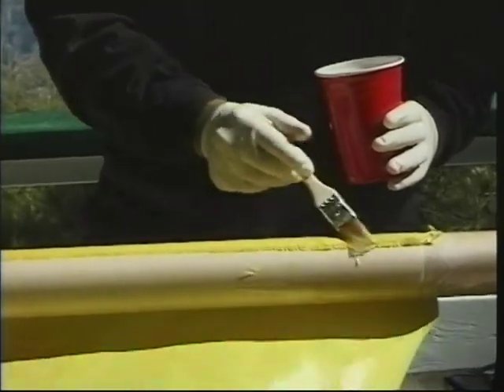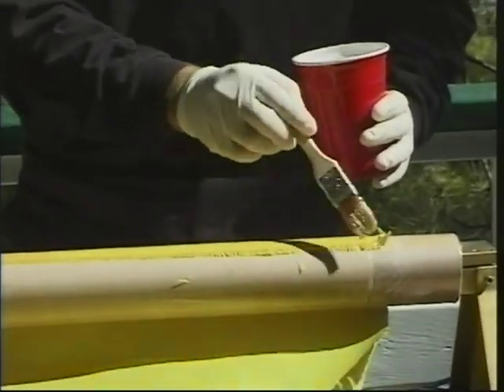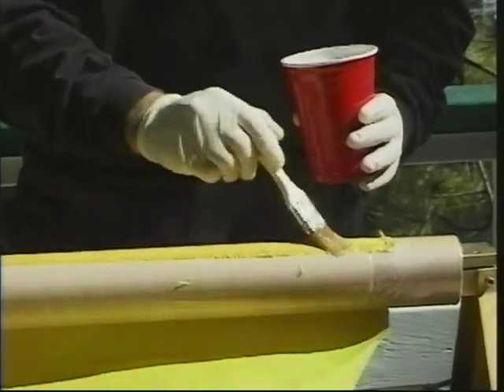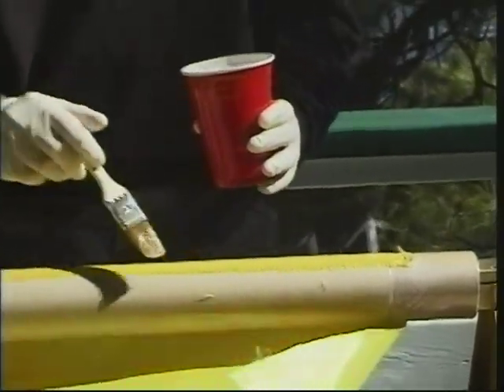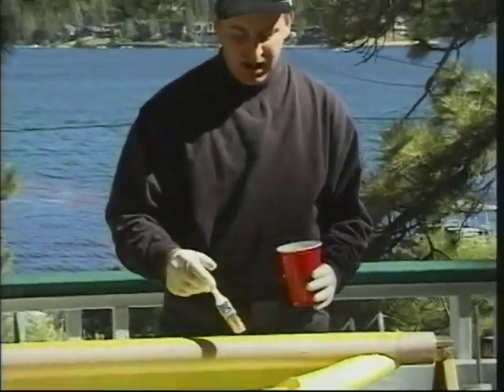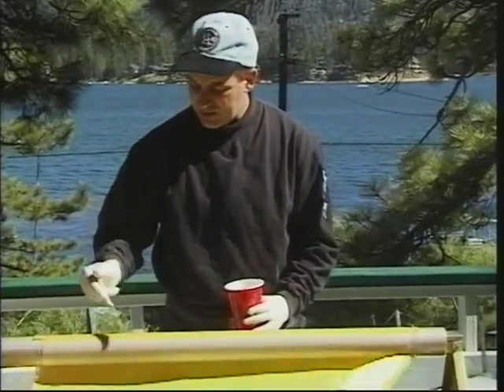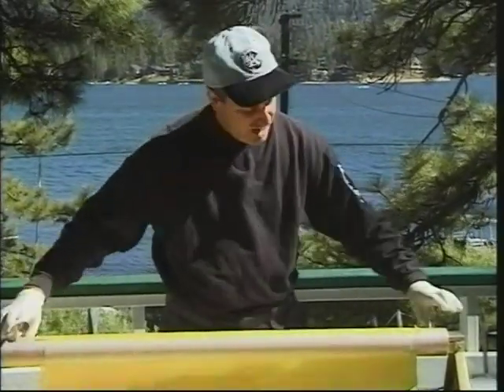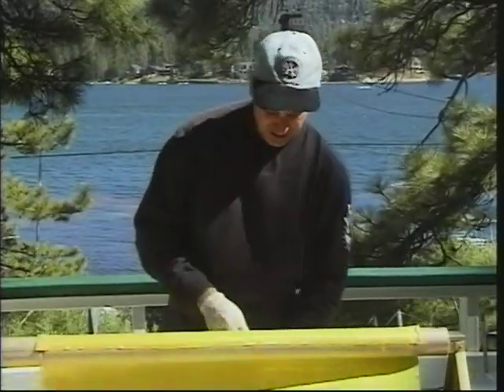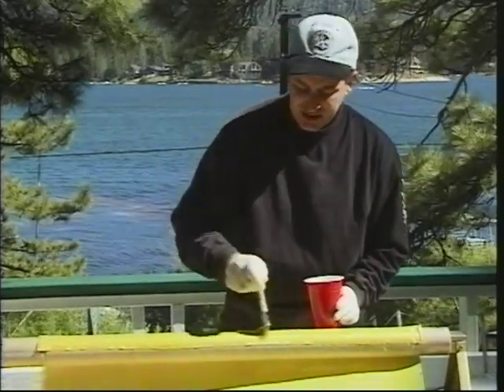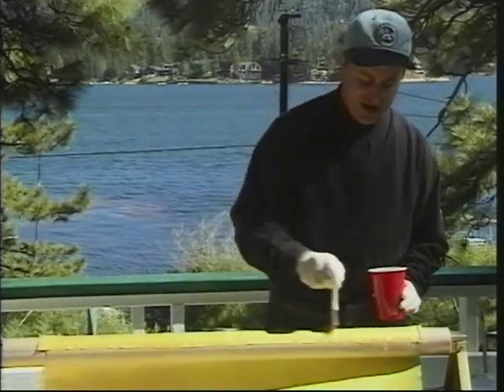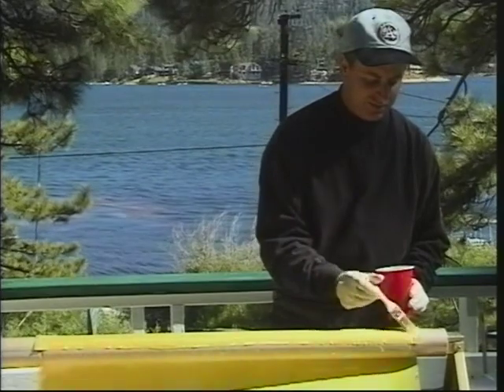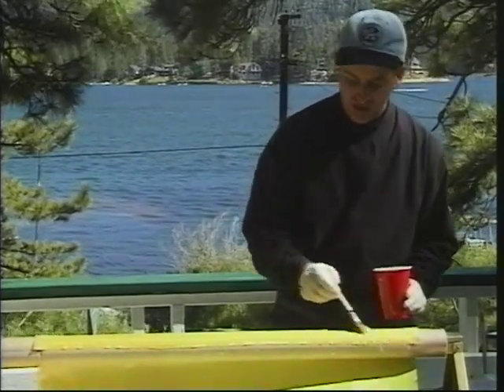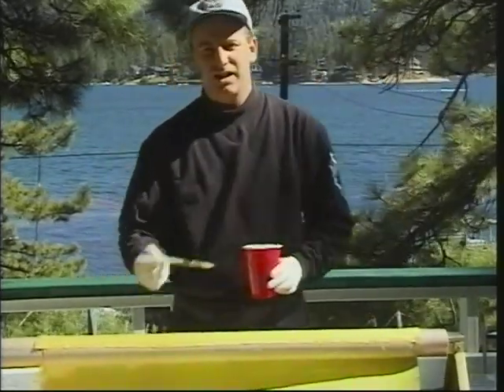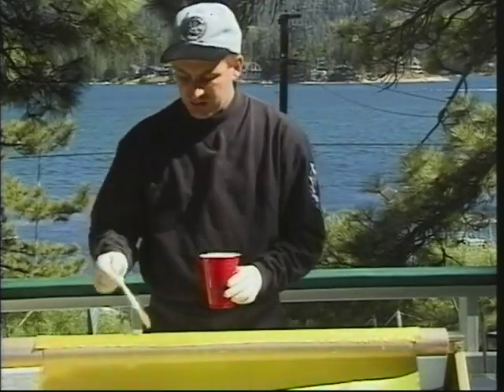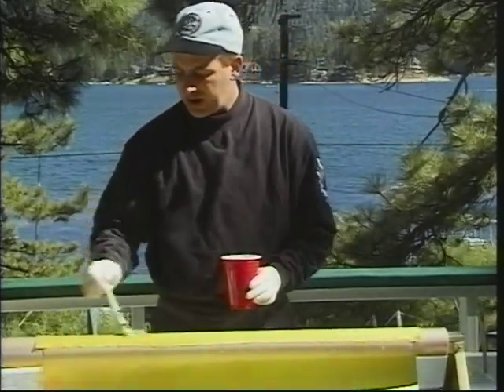We're going to be using the heat tape winding on this material to force those fibers together. And what you'll find is, in the course of your laminate practice, you may notice that that little first edge that you put down wants to stick up sometimes. When you do a dry wrap without any compaction afterwards, you run the risk of getting air bubbles in the laminate.